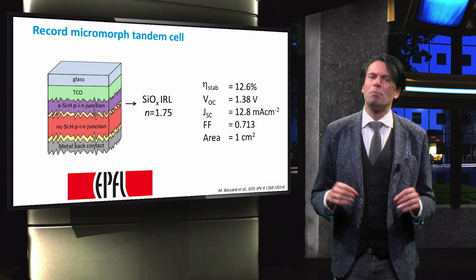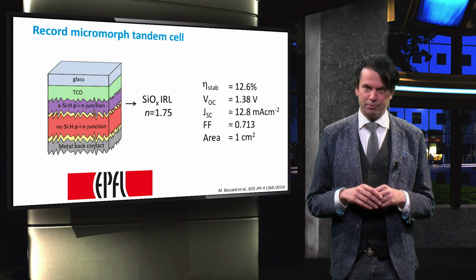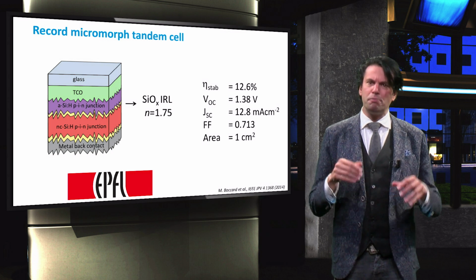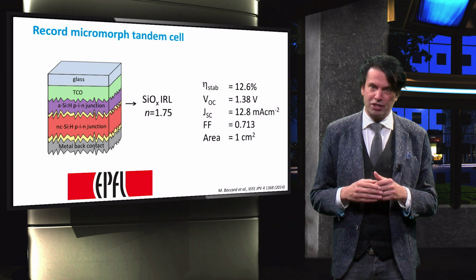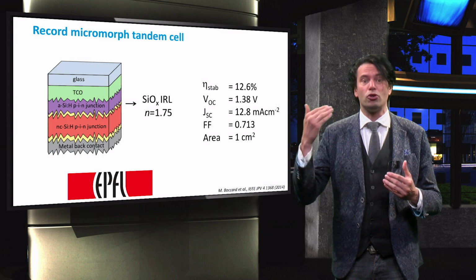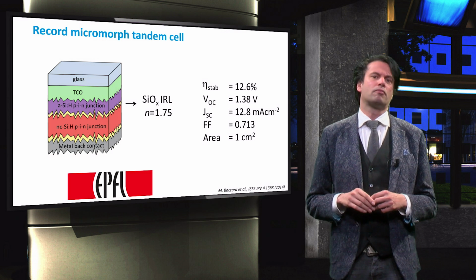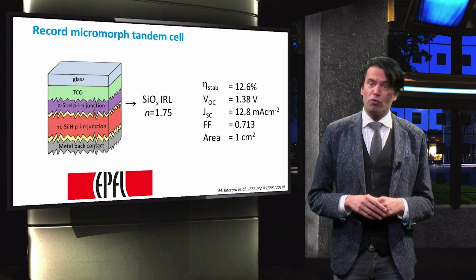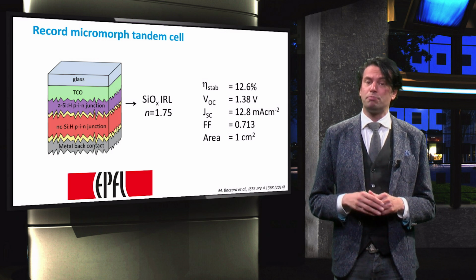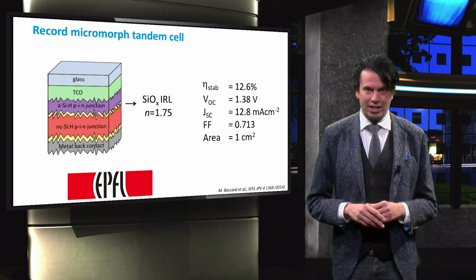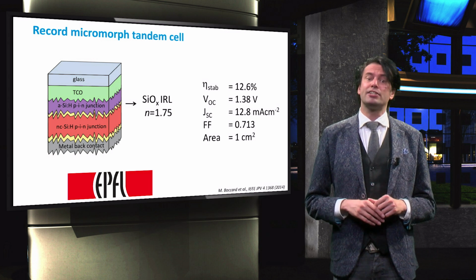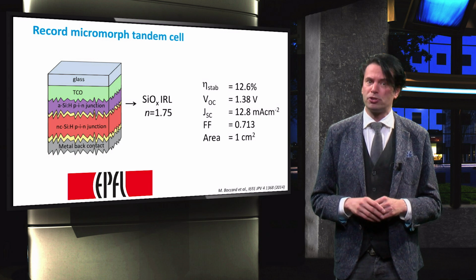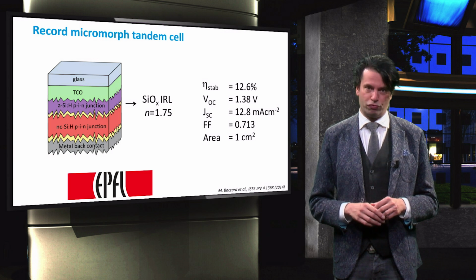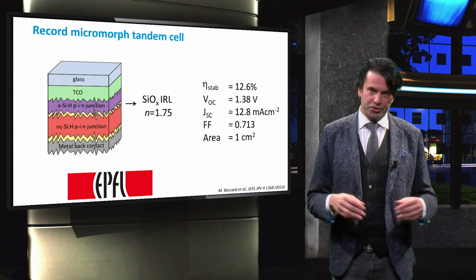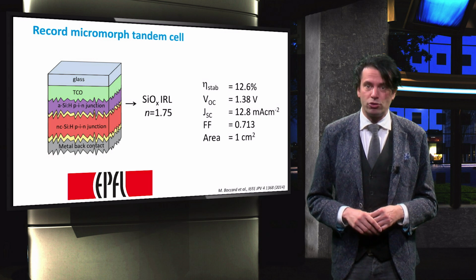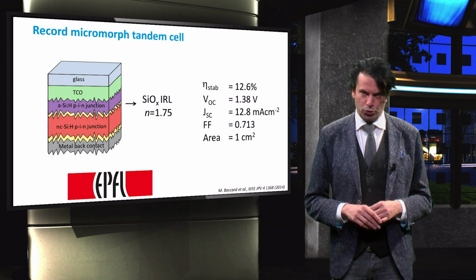This cell suffers from light-induced metastability. Achieving record efficiency means that reduction of the effect of the Staebler-Wronski effect in the top cell is crucial. The record micromorph cell has been processed by researchers at EPFL Neuchâtel in Switzerland. They obtained the record efficiency by using a superstrate PIN-PIN cell configuration. As front electrode, a textured boron doped zinc oxide deposited on glass was used.